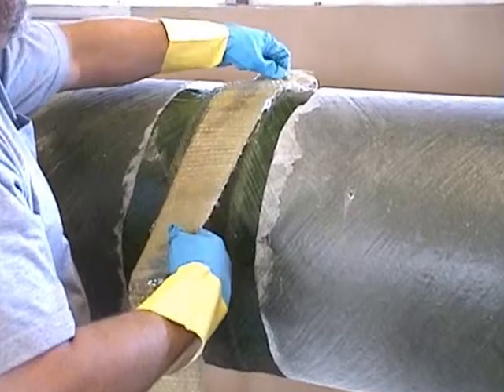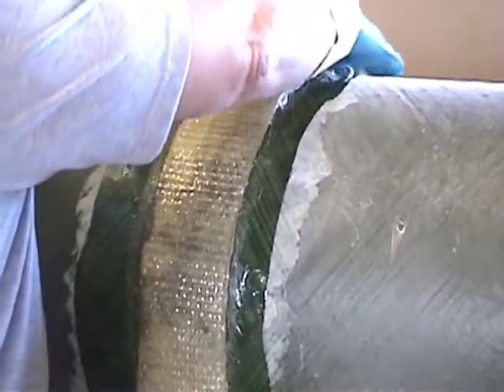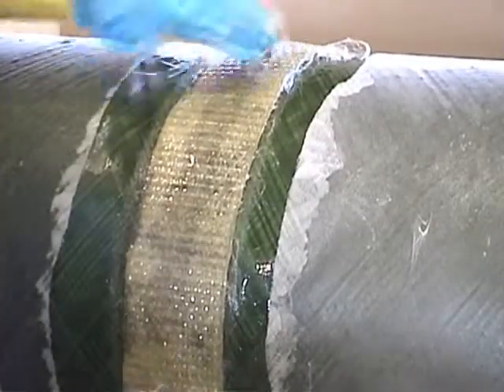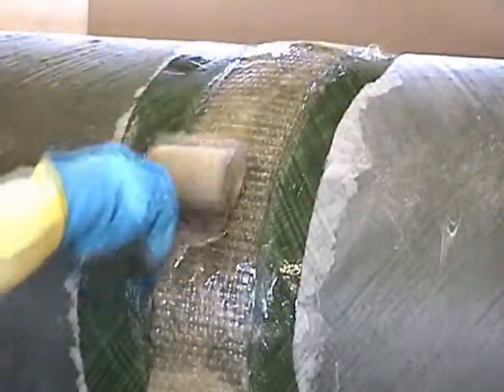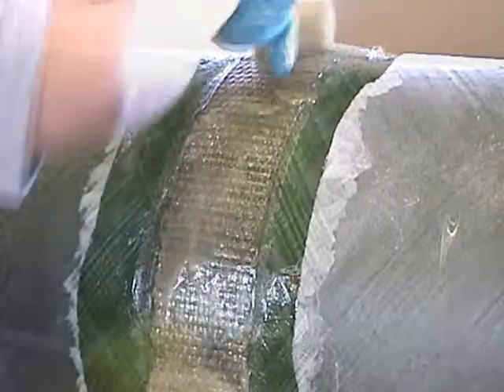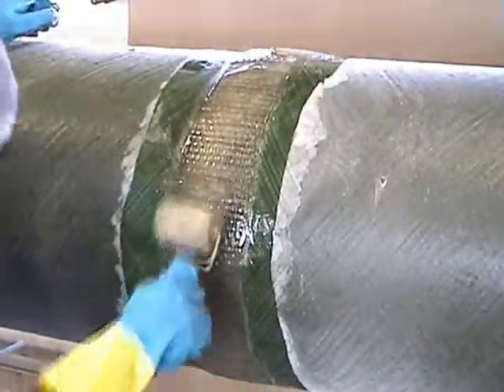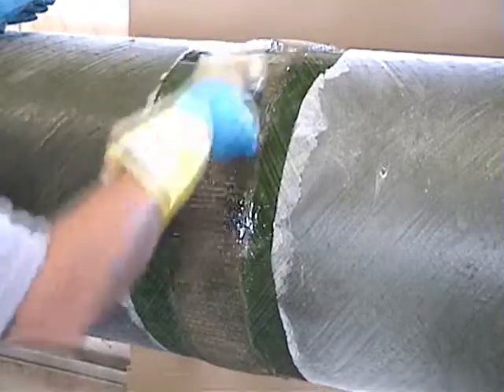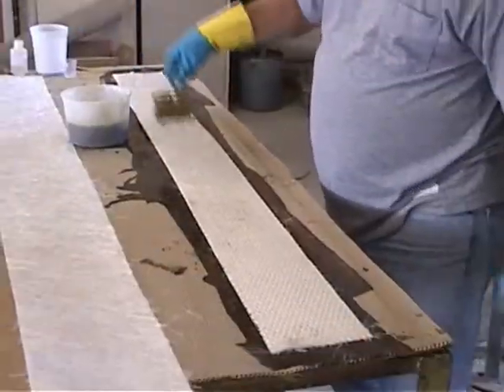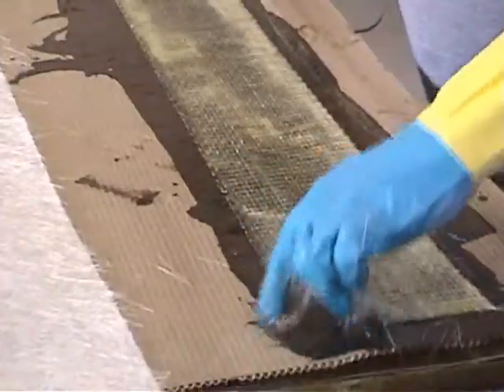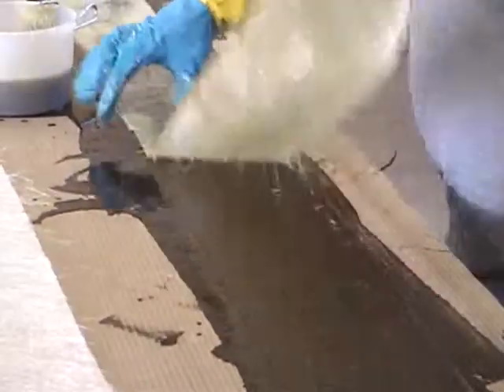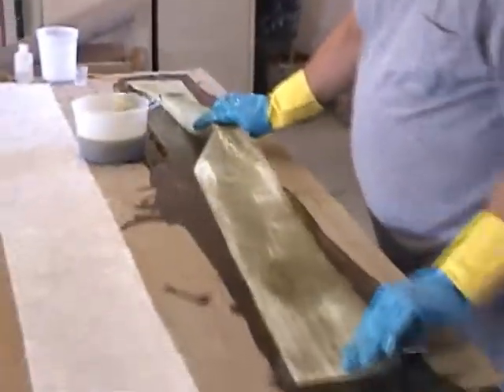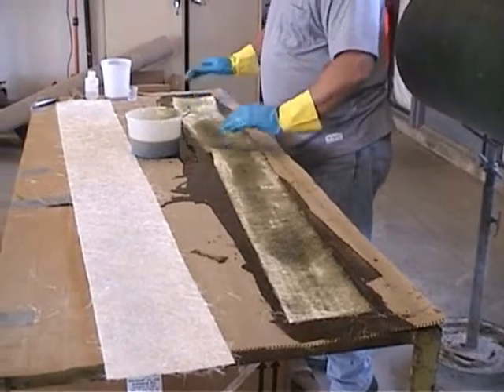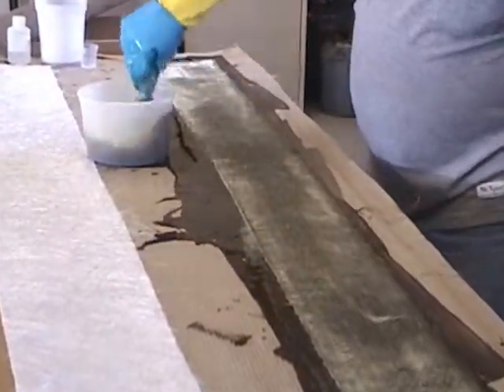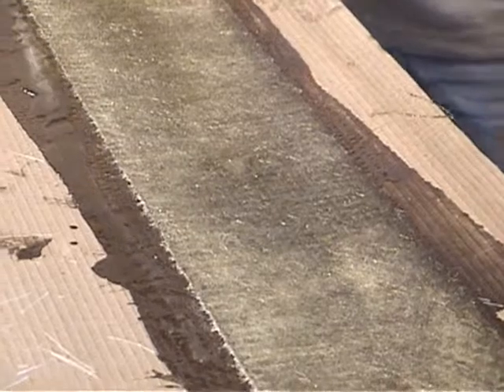Remember, every time you add a new layer, be sure to overlap or stagger the end of the new layer about 3 inches from the end of the previous layer. This prevents a lump from forming where the ends would stack up. Roll it out with enough pressure to roll all the air bubbles out. Next, we roll out resin to the third layer, known as the last layer of structural glass. Roll out the woven side first, then turn it over and wet the chopped strand side.